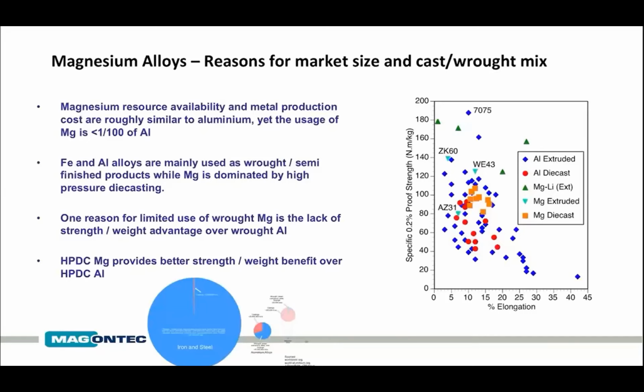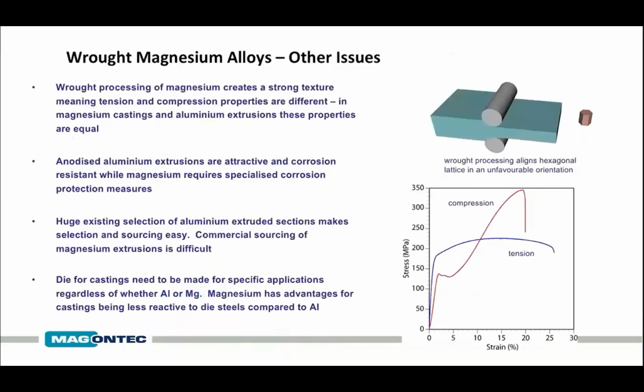So there are a number of reasons, both for the difference in the relative size of the markets for the different metals, and also for the wrought to casting mixture. One of the reasons why magnesium wrought alloys are used so infrequently is strong competition with aluminium alloys, and there's a very wide range of possible properties for wrought aluminium alloys. Whereas for die-cast aluminium alloys, the properties extend over a smaller range. So the comparative advantage, property-wise, is better for magnesium casting stuff.